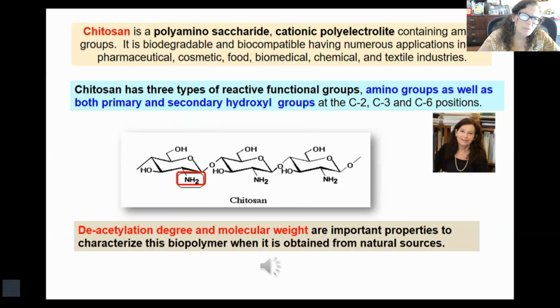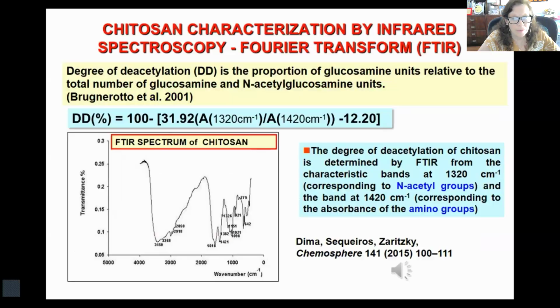Chitosan has three types of reactive functional groups: amino groups and hydroxyl groups. The de-acetylation degree and molecular weight are important properties to characterize this biopolymer. The de-de-acetylation degree is the proportion of glucosamine units relative to the total number of glucosamine and N-acetylglucosamine units. It was determined by Fourier transform infrared spectroscopy, following characteristic bands of N-acetyl groups and amino groups.